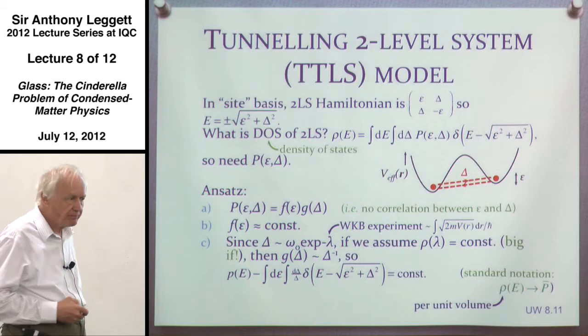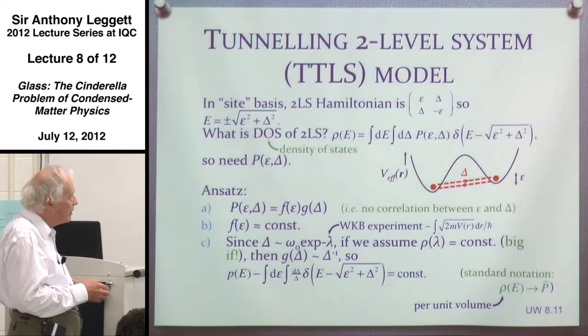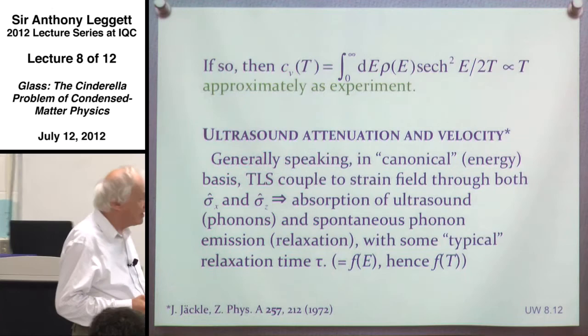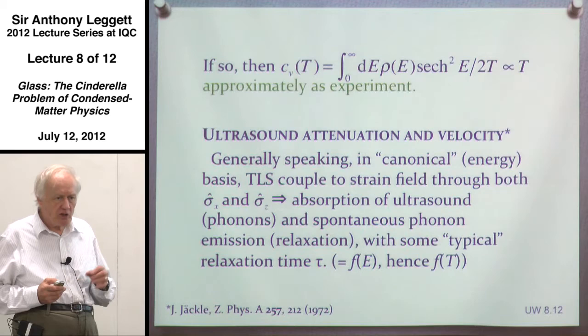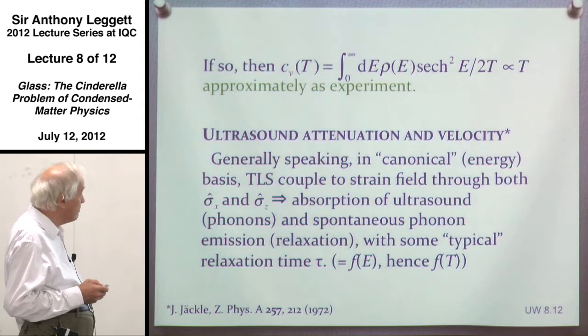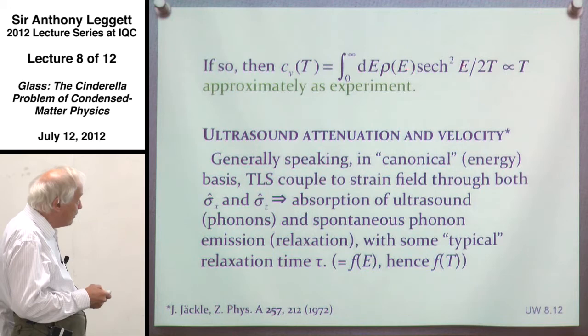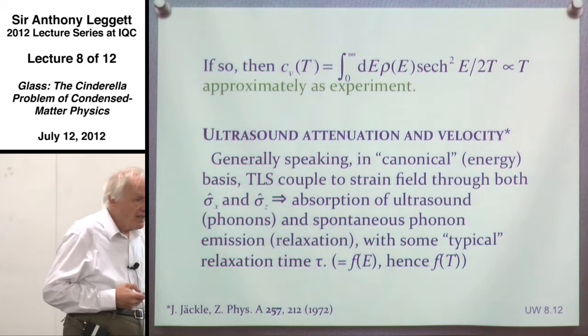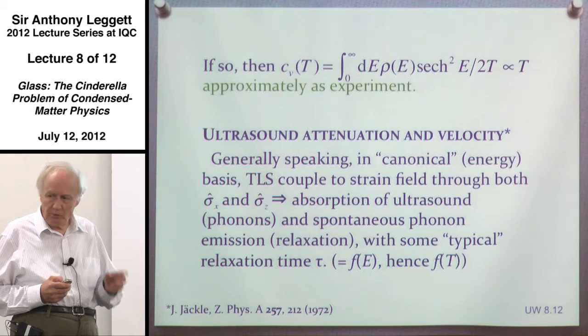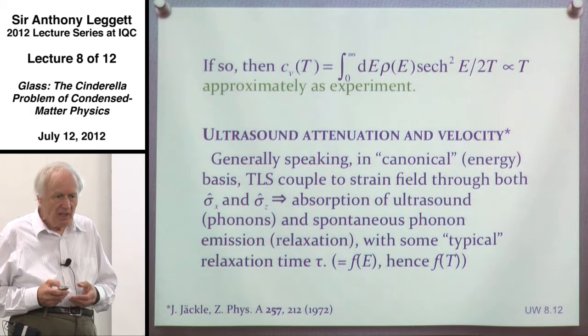What does this buy for you? These two-state systems are essentially analogous to occupied and unoccupied states of fermions — it's as if you had a set of fermions with a constant density of states relative to the Fermi energy. The algebra is essentially the same, and what you find is that the specific heat varies as T, approximately as observed in the experiment. Of course it's not exactly as the experiment, and there are ways of fine-tuning the assumptions about the distributions of λ to make it come out. But by this time, you become conscious that you really are doing an awful lot of adjustment, an awful lot of fudging to get the experimental results.